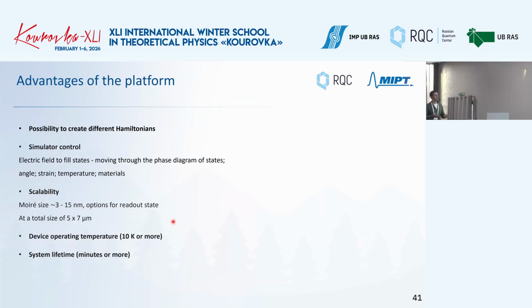The advantages of the platform are the following. There is a possibility to create different Hamiltonians. We can control the simulator by the electric field, strain, for example, temperature, or using different materials. The scalability is quite large. The moiré size is, as we discussed, around 10 nanometers, but can be larger or smaller. And the sizes of the samples are around 5 to 7 microns.